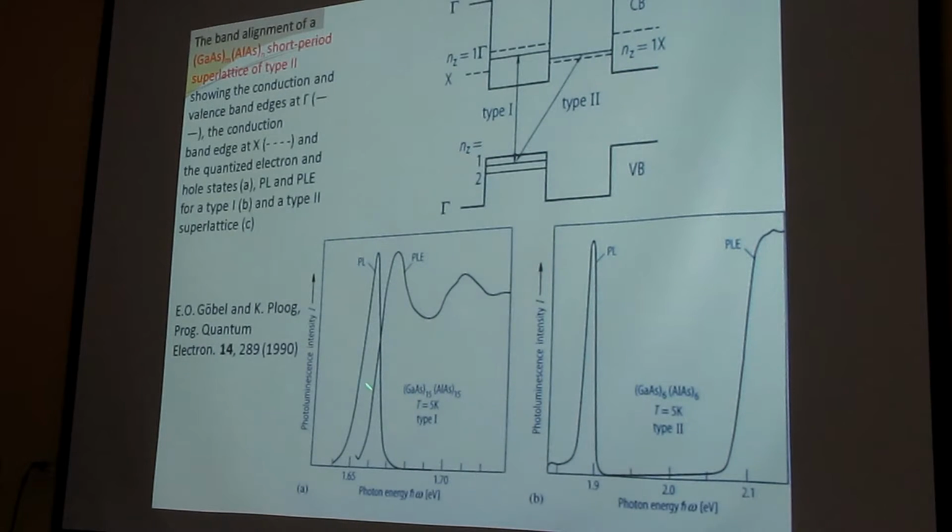And this is a relatively long period superlattice here in the luminescence spectrum, and here not the absorption spectrum but the photoluminescence excitation spectrum, which we hope coincides approximately with the absorption, almost coincide. This is a much narrower situation, and here you have really an energetic distance between the two, and this absorption here is very weak. This means you get only a weak absorption for the spatially indirect transition, and the real absorption starts only here. But the luminescence, the electrons drop down here, the luminescence comes at low temperature from this indirect transition.